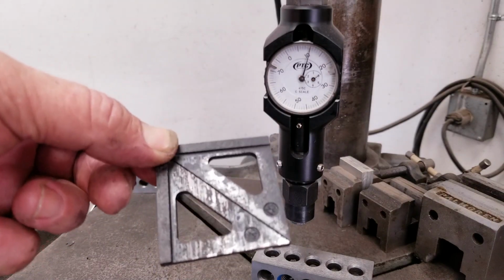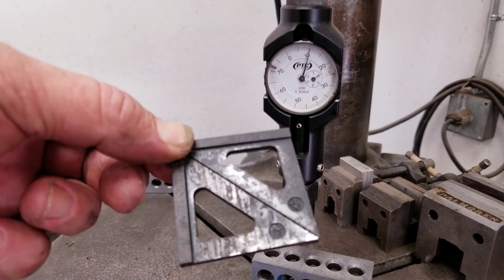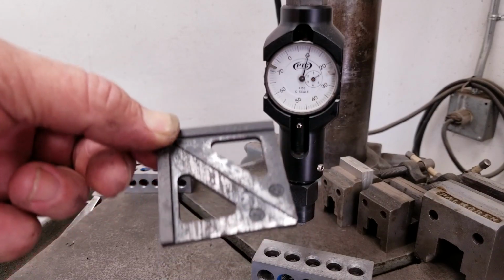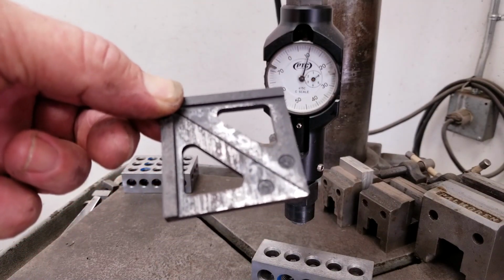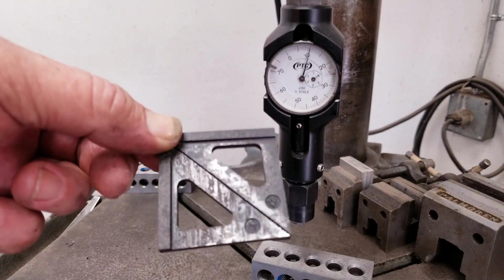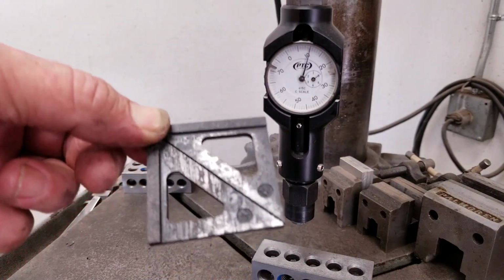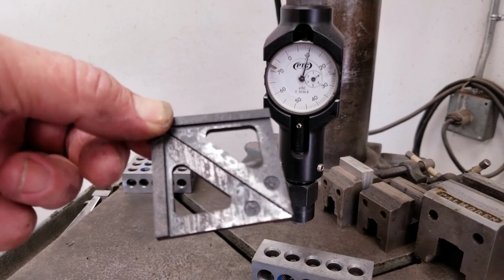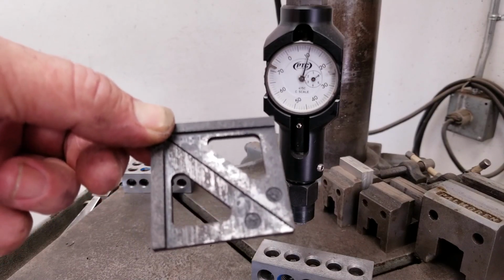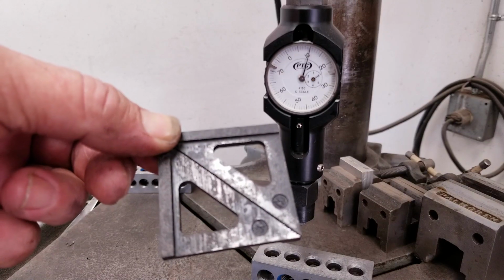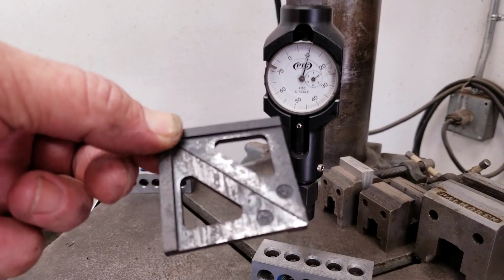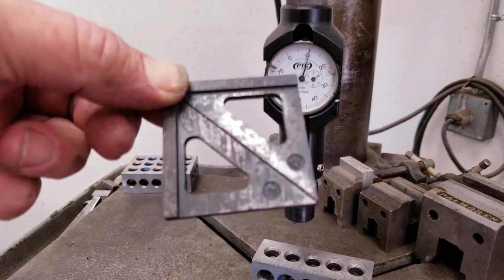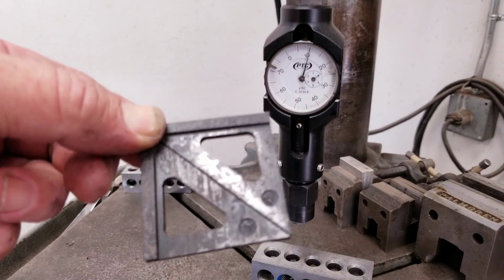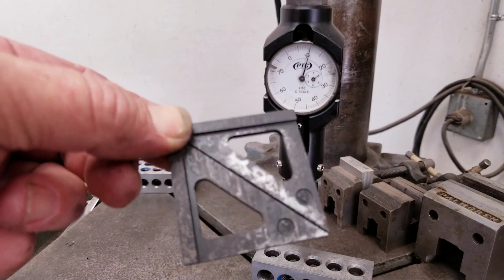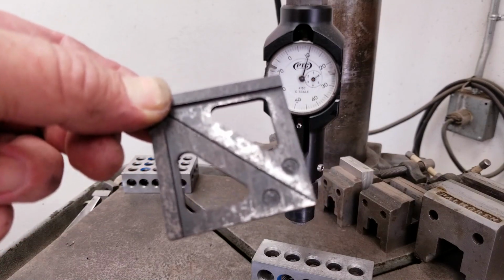Now I did this just to show you how hard they get. In the real world, what I do is I heat treat, I quench in oil, and then while the parts are still hot, I get them in the oven at tempering temperature. You don't let them completely cool the way I've done here. So this was just for demonstration purposes. All right, so let's go get them tempered and see how soft we can get them. Right now we're about 64, 65 Rockwell C.